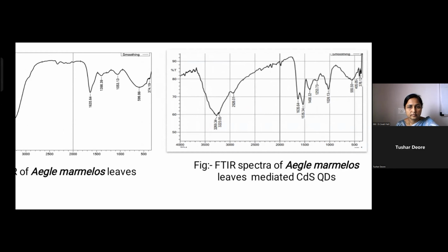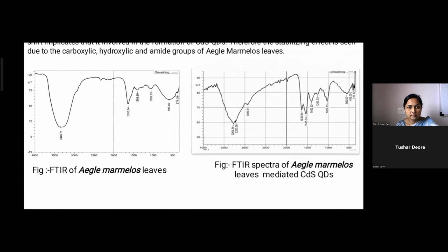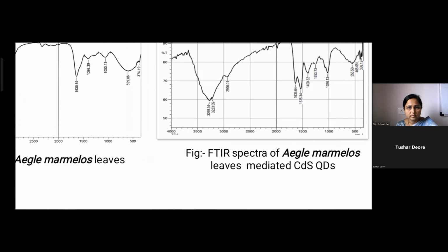In the figure, we can see that the main peaks are 3340.71 inverse centimeter for the Aegle marmelos extract, and 3269.34 for the synthesized CdS quantum dots. The shift between these points, from Aegle marmelos to CdS quantum dots, implicates the involvement of these functional groups in the formation of cadmium sulfide. From the wavelengths, we can see the carboxylic, hydroxylic, and amide groups from the Aegle marmelos extract.